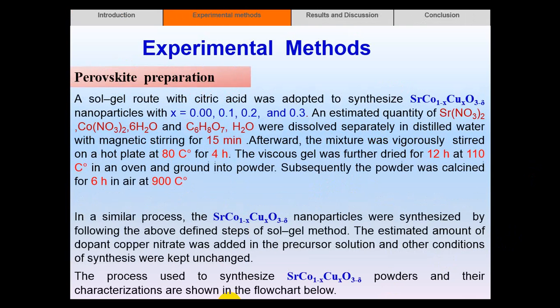Now, experimental methods, perovskite preparation. A sol-gel route with citric acid was adopted to synthesize SrCo1-xCuxO3-δ nanoparticles. An estimated quantity of strontium nitrate, cobalt nitrate, copper nitrate, and citric acid were dissolved separately in distilled water with magnetic stirring for 15 minutes. Afterward, the mixture was vigorously stirred on a hot plate at 80 degrees Celsius for 4 hours.